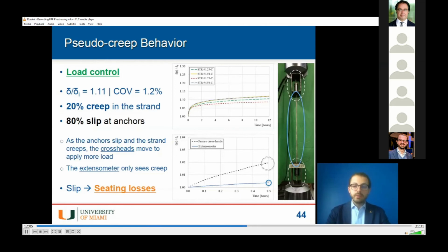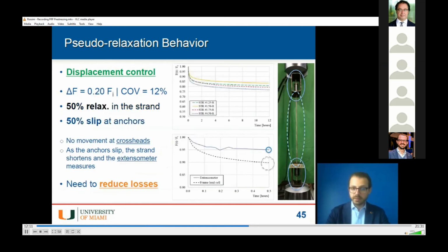Of course, if you have slipping at the anchor location, you should expect some load losses. And that's why we also conducted some pseudo-relaxation tests that were aimed at measuring these losses, which amounted to up to 20% of the initial load that we were applying. And also in this case, we were able to measure this by applying an extensometer, and we noticed that most of the losses, or at least a good portion of them, were caused by slipping at the anchor location.